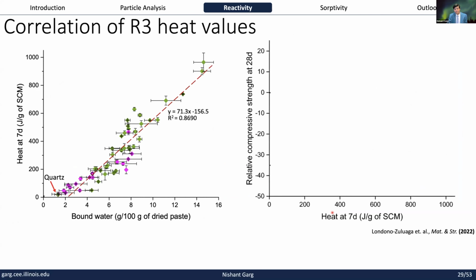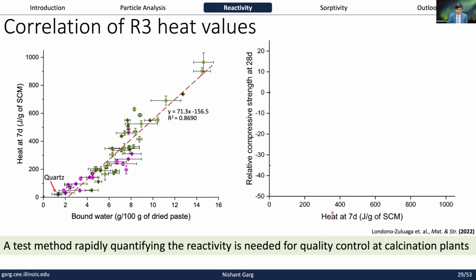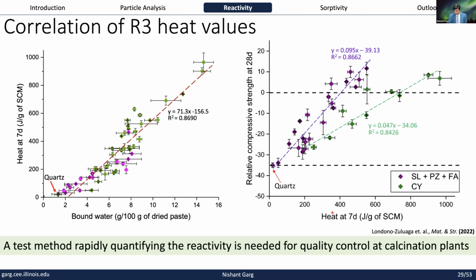Just to give a brief insight on the R3 test, you can do it either by the cumulative heat method from calorimetry, or you can do it with the bound water method. And the bound water method has now also entered one of the performance-based specifications at ASTM, which means there will be a lot more data coming out on this test.